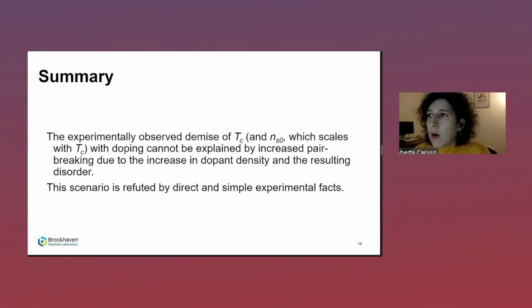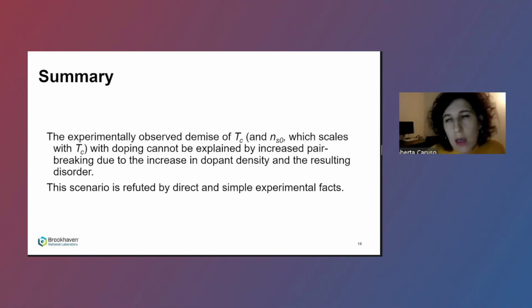We also know from other measurements and previous work that we are somehow electrochemically doping the devices. So there is a disorder caused by implantation of ions from the ionic liquid. But with this kind of measurements, this is pretty much all we can say about disorder, the type of disorder that we create.